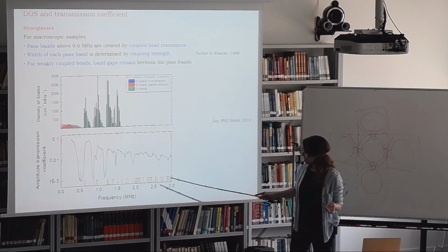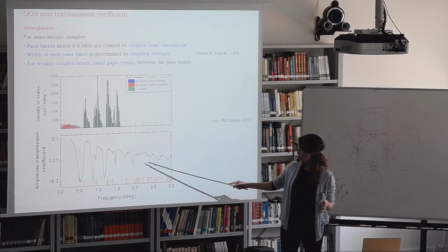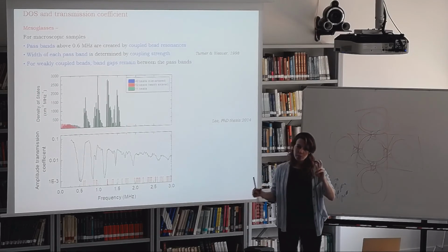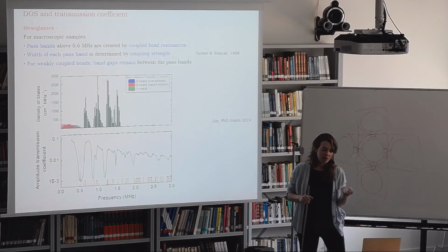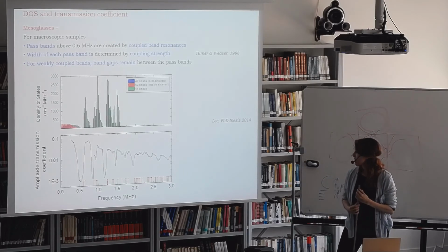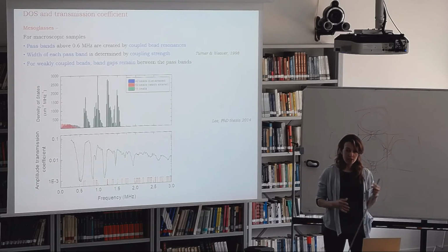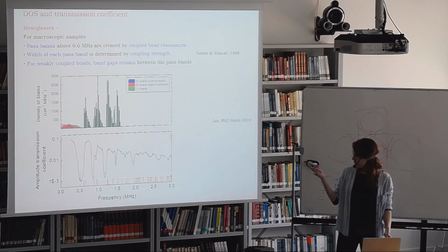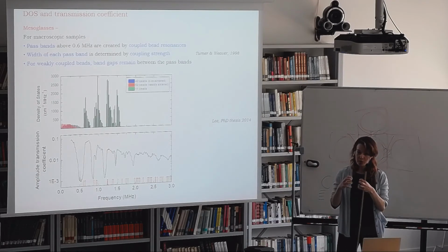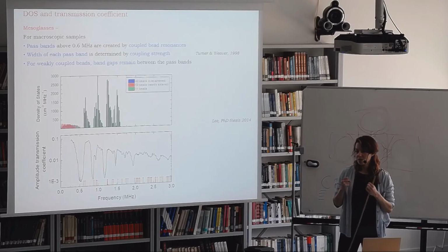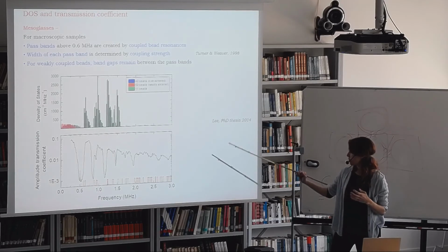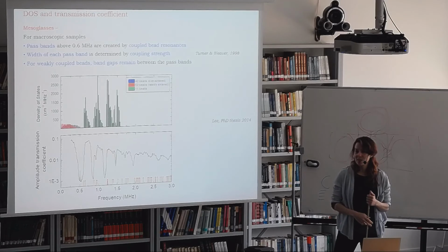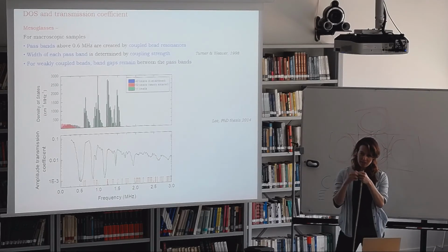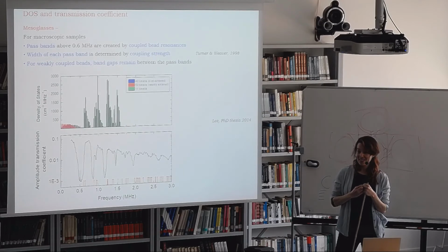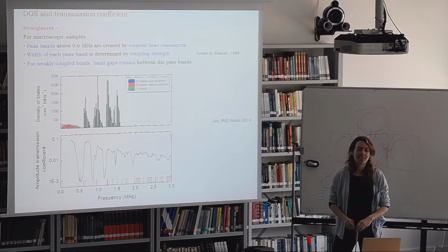And so actually we've seen that localization tends to occur more in these band gaps, or transmission gaps is better to call them. And so these can be enhanced by having less coupling between the beads, so that you have this more extreme effect. Does that make sense? So one way to do that would be to have smaller necks joining the beads. Okay. Does that make sense? Yeah, it's an answer.